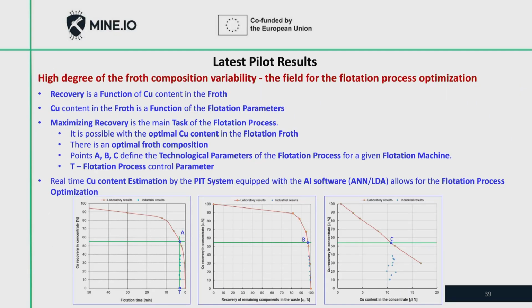And with that knowledge, with that possibility, we opened the path for flotation process optimization. Because we can get this information very quickly, we can react very quickly in terms of machine control. We already know that the recovery in the process has a relation to the copper content in the froth, and the copper content in the froth is related to the flotation parameters. So by setting the flotation machine in the proper way, we can try to control the process to work on optimized parameters in terms of flotation time, recovery, and the Cu content in the final concentrate.